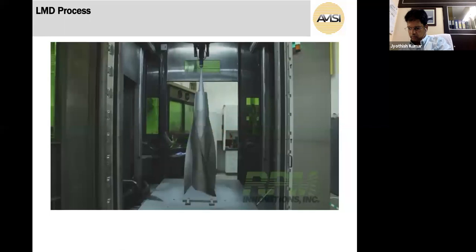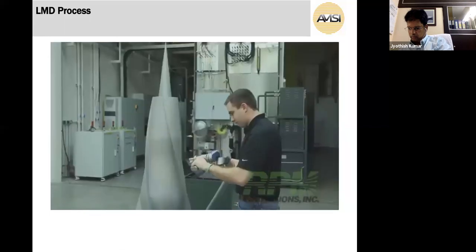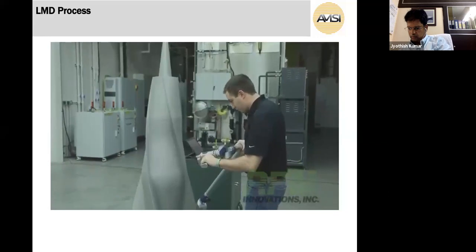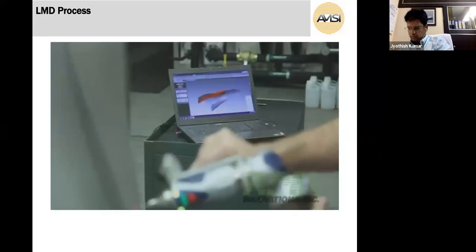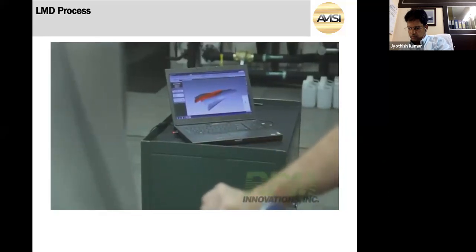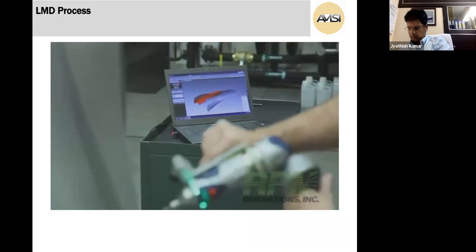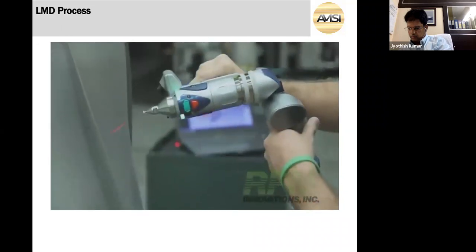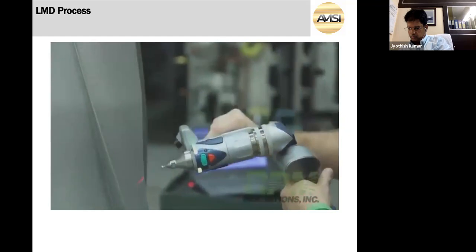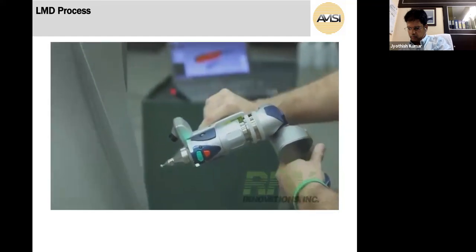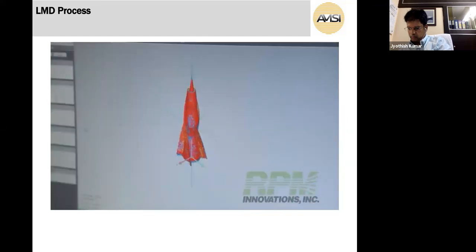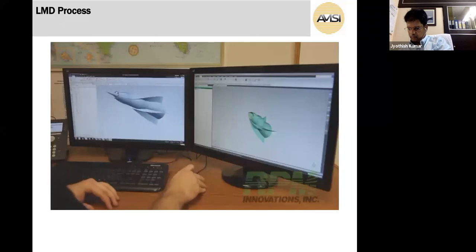After a build is completed, the component is scanned using a portable CMM and scanning laser. The scanned file is compared to the original file to be certain no significant distortions have occurred and that enough material has been deposited to ensure cleanup during final machining. Minor discrepancies are carefully noted so that future potential distortions can be compensated for and therefore avoided.